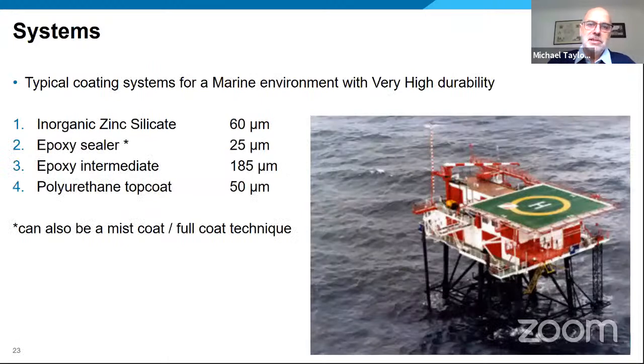So a typical coating system for a marine environment with very high durability. This wouldn't be offshore. This picture's a little bit misleading, but this would be a coastal environment, for example, for the zinc silicate. A total of 320 microns will be shown there. I mentioned there about the epoxy sealer to prevent the pinholing of the coating system.